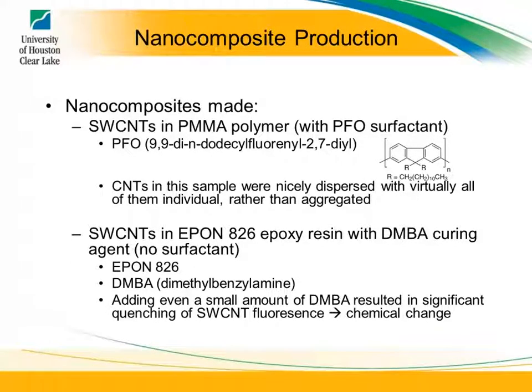Well, it turns out with a surfactant, you can overcome all that bundling. If you look there, there's lots of nanotubes there, and they're all conglomerated together. There's very large van der Waals force of attraction between nanotubes. The surfaces just come together and they stick together, and it's very hard to separate them apart. If you want good dispersion inside materials, you've got to be able to separate out the nanotubes. That's one of the biggest hurdles that material scientists are trying to jump over. That's very, very difficult.